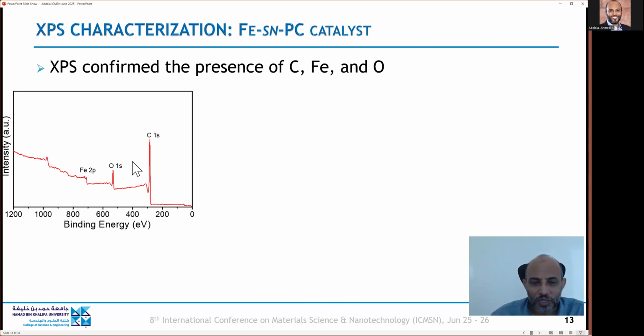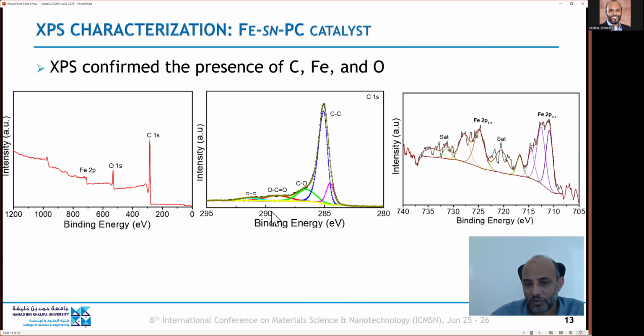We confirmed the presence of iron and carbon, and of course oxygen, from the mesoporous carbon using XPS. And you can see the mesoporous carbon has mostly carbon-carbon bonds, but there are also some carboxylic groups and maybe some epoxy groups present in the mesoporous carbon.